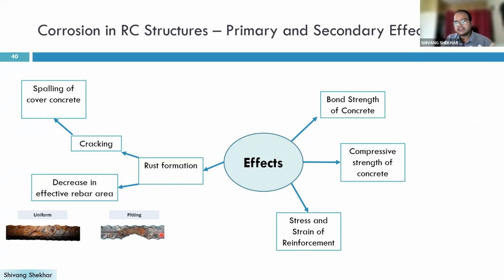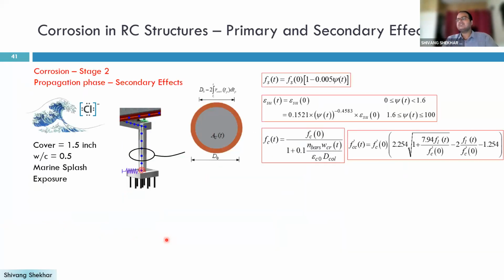Now, in addition to that area loss, I have already said that pitting corrosion also leads to secondary effects of corrosion, like spalling of the concrete or reduction in the cover strength of the concrete. The reinforcement corrosion of the ties also leads to the reduction in the confinement. So that also happens, the spalling of concrete and all. So there are different secondary effects. Also, due to non-uniform reduction in the cross-sectional area, steel mechanical properties like strength and ductility also get reduced.